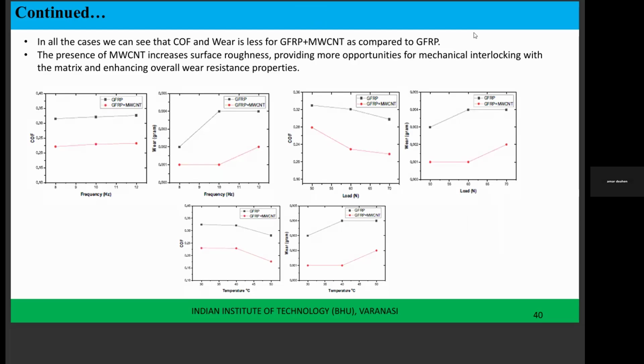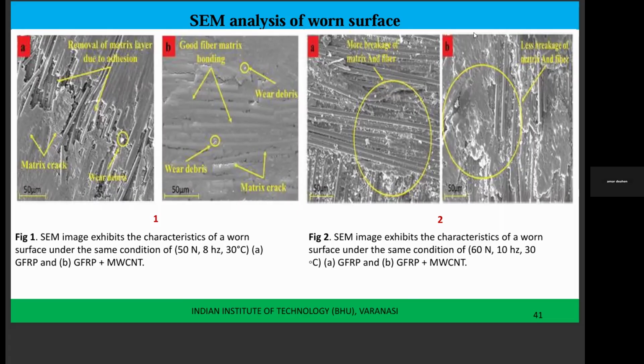With increasing frequency, and also with increasing load and temperature, we have studied how the coefficient of friction is changing. Next slide, please. We have also visualized at the micro level how the bonding between the matrix and the fiber behaves in the CNT case. Without the multi-wall carbon nanotubes, you can see more matrix layer has been removed, there is matrix cracking, and more debris is formed. But when you add the multi-wall CNT, there is good fiber matrix bonding and very little matrix cracking. Similarly for the worn surface under the same condition, with a load of 60 newtons, frequency of 10 hertz and 30 degrees centigrade, for both the glass fiber reinforced plastic composite and the GFRP mixed with multi-wall carbon nanotubes polymer composite. Next slide, please.